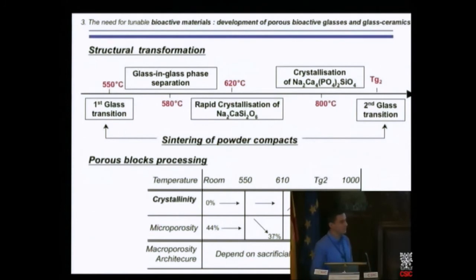What we have shown is that using bioglass powders, you have the opportunity to profit from some transition and crystallization process. When you take a bioglass, at 550 degrees C, you have a first glass transition, then the glass-in-glass separation, and then the rapid crystallization of this crystalline phase. Then at this temperature, you have a crystallization of a second phase, and if you go towards larger temperature, you have a second glass transition. So you can play with this crystallization process to sinter nanostructured glass ceramic porous bodies. And we have shown that the crystallinity changes the bioactivity of the bioglasses.